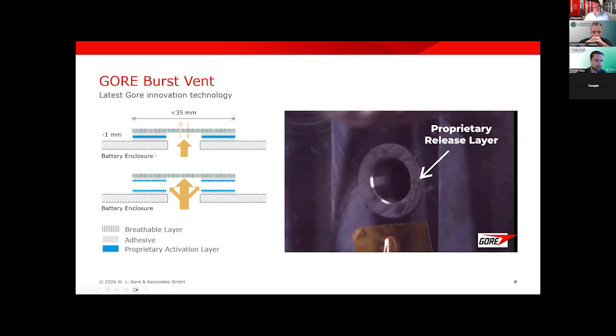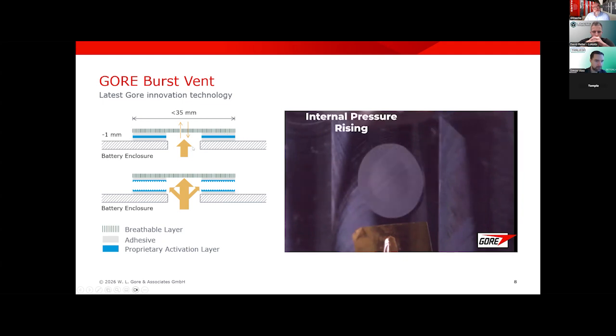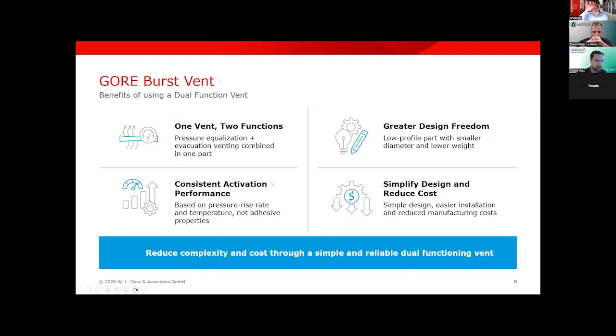But this is not the disc itself, so the whole breathable layer is stuck to the battery enclosure with 2 adhesive layers and a proprietary activation layer. This activation layer, this is bursting if a certain pressure is reached. So the benefit in using a dual function vent is having only one vent with 2 functions with a consistent activation performance, and you're having greater design freedom because of the low profile part with the smaller diameter and a lower weight. So this could simplify the design and reduce costs.